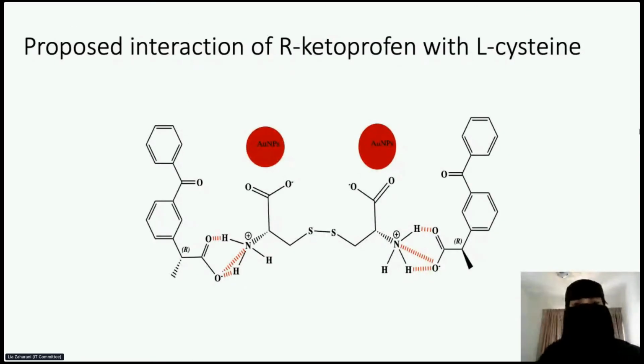So this slide proposes an interaction of R-Ketoprofen with L-Cysteine, representing the three-point contact model for chiral recognition in biomolecular systems. Functional groups such as amino, hydroxy, as well as carboxylic acid play a key role in the chiral discrimination by electrostatic and hydrogen bonding between the R-Ketoprofen and L-Cysteine. So this indicates a potential theoretical colorimetric detection method for Ketoprofen enantiomer, as illustrated here.